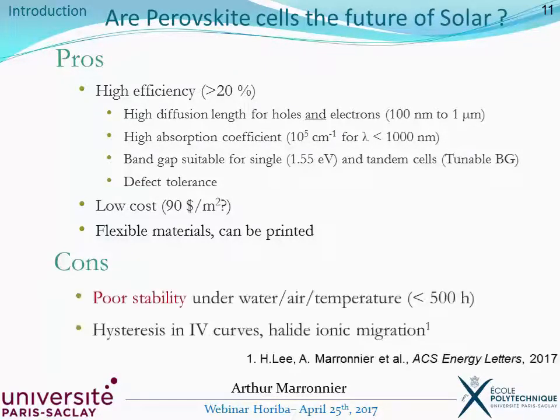But on the other hand, they've shown poor stability under different conditions such as humidity, oxygen, and temperature. And today, in general, the stability does not exceed a couple of hundred hours. Another point is that they've shown a hysteresis in their IV characteristics. And this hysteretic behavior has been mostly attributed to a halide ionic migration inside the perovskite layer, as we evidenced in a work that we published last month, also together with HORIBA company in the Journal of ACS Energy Letters.